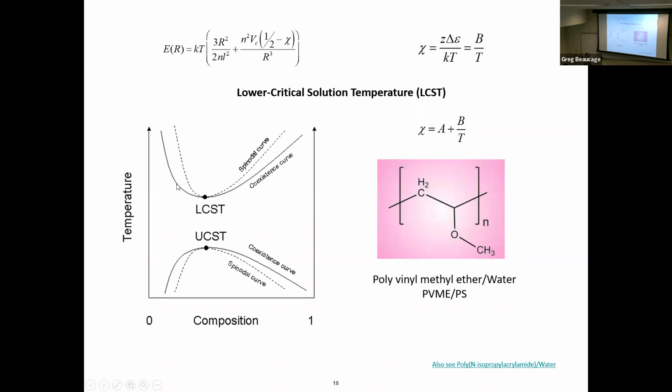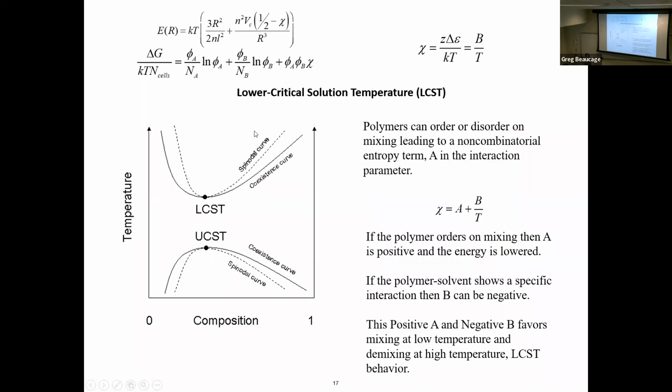And at that temperature, that's the binodal. So if you can get 2 points on the binodal, you can predict the entire coexistence curve, the entire binodal curve, and then you can also predict the entire spinodal curve and the critical point based on the Flory-Huggins equation. You just need 2 points on this and you can get this whole equation. And you can predict the entire phase behavior of the system, and it works really well. It works almost perfectly. There's a few nuances, but it's incredible how well that works to predict polymer phase behavior.